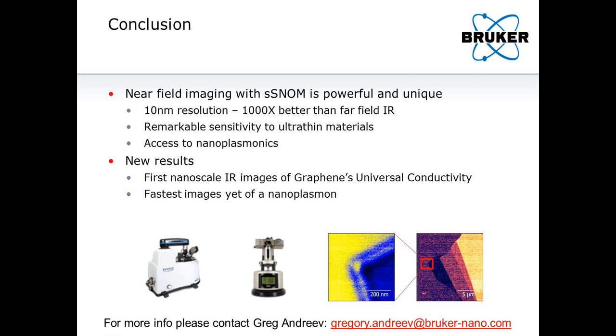Sure. A resonant material is one that has absorption at the infrared frequency you're using. One example is a molecular resonance, the same sort of resonance that leads to absorption dips in an infrared spectrum, such as the one I showed at the very beginning of the presentation. If you tune to one of those absorption lines, you would be near the molecular resonance of that material. Another type is a plasmonic resonance, where you have charge density waves on the surface of the material that you can excite. So those are the two types of resonances I'm referring to.